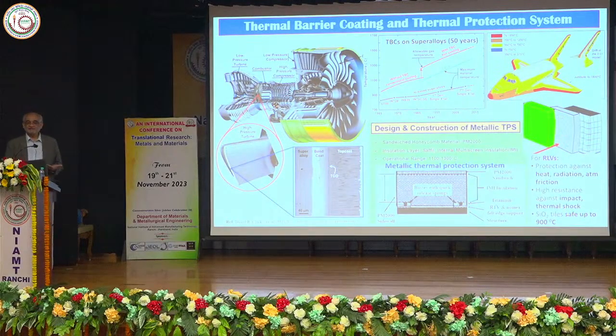The disadvantage is that while they fit the bill in terms of creep, fatigue and so on, they are non-fusible. So you can't join them, and you can't make a convoluted or complex shape out of that because they are not really deformable. So you need tiles, and when you join tiles, the tiles at the interface may fail, and this is exactly the reason we lost the brilliant astronaut Kalpana Chawla.